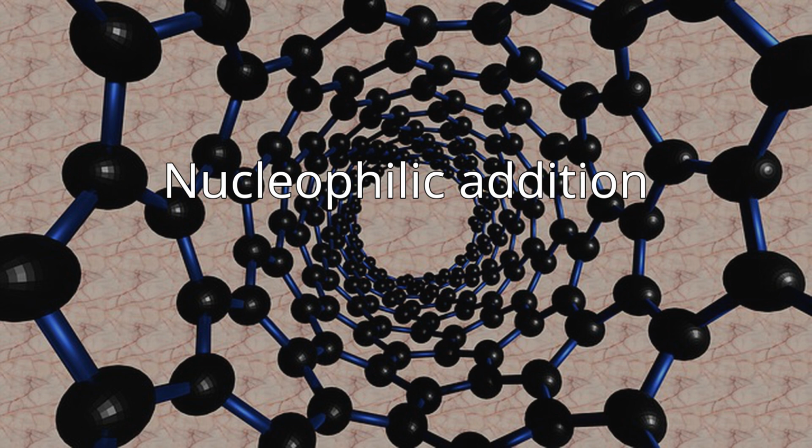Nucleophilic addition. Hirsch et al. conducted nucleophilic additions with organolithium and organomagnesium compounds onto carbon nanotubes. With further oxidation in air, they were able to create alkyl-modified carbon nanotubes. Hirsch was also able to show the nucleophilic addition of amines by generating lithium amides, leading to amino-modified carbon nanotubes.